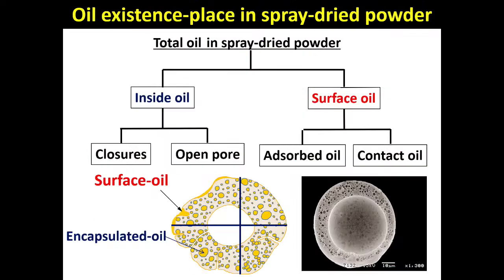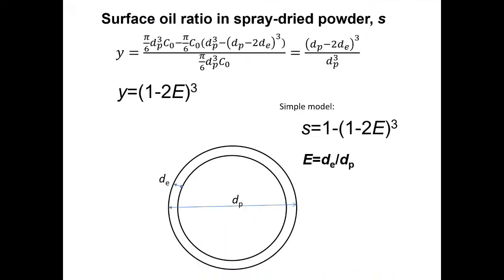This slide shows where the oil exists in spray dried powder: inside, and surface oil. Surface oil means adsorbed oil or contact oil. And then the inside oil, closed pores, open pores. Therefore, when we make the powder, the amount of encapsulated oil is important. Surface oil is easily oxidized in oxidant conditions.